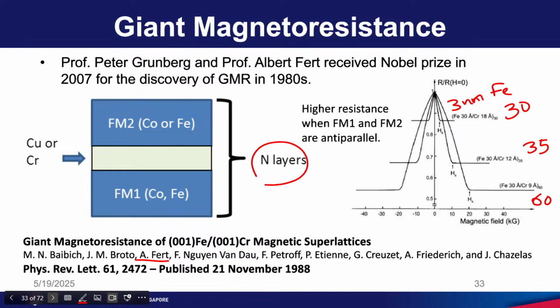And chromium is different: here is 18 angstrom, here is 12 angstrom, here is 9 angstrom. So, they have 3 different types of multilayers, and they measure the resistance of this device as a function of magnetic field. What they observe is that the resistance is high when the magnetic field is 0, and if you increase the magnetic field, the resistance drops. For this particular set, the resistance drops to this value.